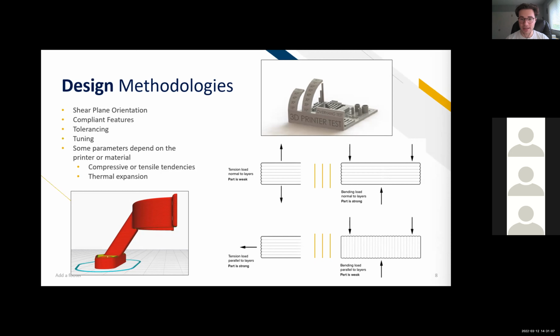One thing when you're designing these bendable components is always make sure that the extrusion direction is orthogonal to the plane in which the bending is going to be induced. When you try to bend something, when it's weak or when the layers are stacked up in the bend direction, it will very often start to delaminate and you won't notice it right away, but your part will have a critical failure.